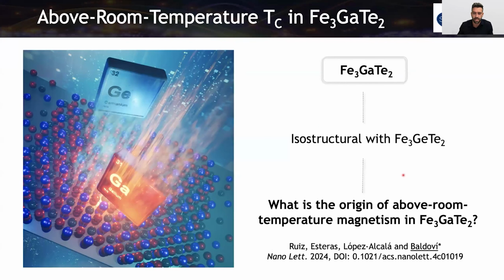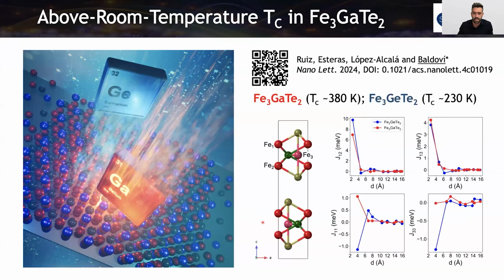Then more recently, we have also investigated the properties of iron, gallium, tellurium. This is a very interesting material now because the Curie temperature is above room temperature. And as the material is isostructural with iron, germanium, tellurium, we also want to compare the properties and investigate why in this case it is much higher. So what is the origin of the above room temperature? We have been working on that, in this very recently published paper in Nano Letters. The idea is to study these two, gallium and germanium, to understand these effects.